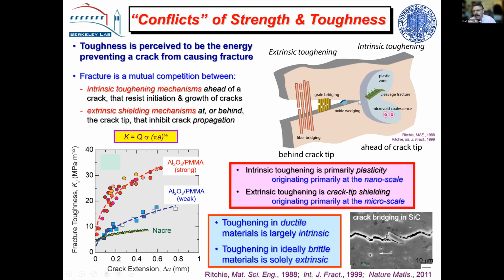Deflection at the crack tip is another mechanism. And if you're dealing with fatigue, then there's a wedging mechanism called crack closure. Now, these originate at any scale, mostly at the micro scale, but at any scale. And these are the mechanisms that operate basically to promote toughness in brittle materials. In fact, there's not much other ways you can do it. But both these mechanisms involve phenomena behind the crack tip, and of course, extrinsic are inherently behind the crack tip, but even with intrinsic toughening, as a crack grows, it leaves plasticity behind the crack tip.